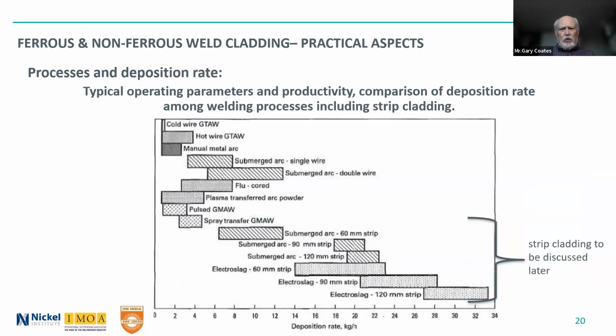So this chart shows different processes and the deposition rates. And if you're doing a large job, of course, the sub-arc is very effective. But if you use the sub-arc double wire process, you can get even higher deposition rates out of that, probably without much change in the dilution. And the bottom ones are actually strip cladding, and we're going to discuss that separately.